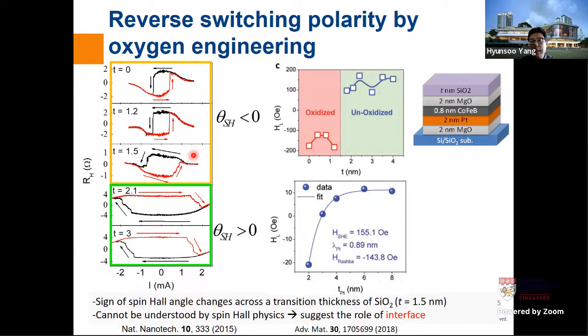Maybe let me use the laser pointer. But on the other hand, once we make the silicon oxide less than 1.5 nanometers, we find the switching sequence is opposite, as you can see in these yellow boxes. This indicates the effective spin Hall angle is negative here. So depending on the capping thickness of silicon oxide, you can see the effective longitudinal spin-orbit field becomes negative. So this is very strange. It's impossible to understand by spin Hall physics, and this suggests some role of the interface. So at that time, we interpreted this as also a contribution of the interfacial Rashba effect due to oxidation.